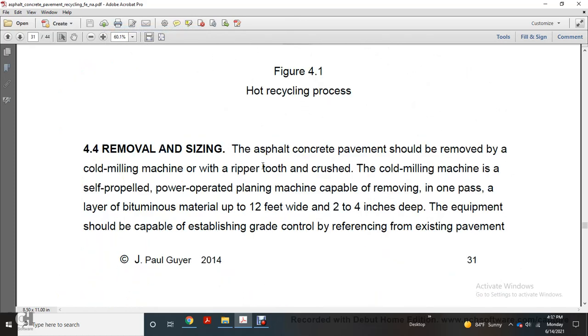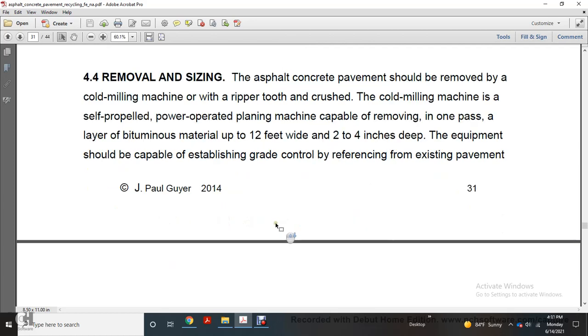Alright, 4.4, removal of the existing pavement. The asphalt concrete pavement should be removed with a cold milling machine or a ripper and crusher. The cold milling machine is a self-propelled, power-operated planing machine capable of removing, in one pass, a layer of bituminous material, up to 12 feet wide, with 2 to 4 inches of depth. The equipment should be capable of establishing grade control with reference to the existing pavement.